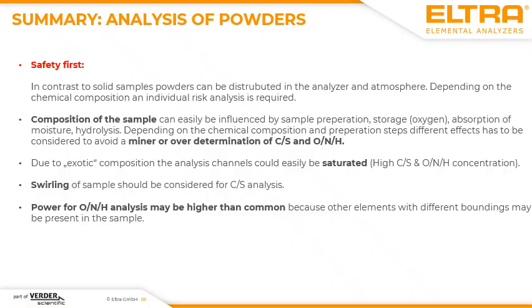Due to the high concentrations in these slags, for example, or powdered samples, it could be that you cannot process your sample in, I would say, a way which is common for you. For example, when you have very high concentrations of oxygen or nitrogen inside the sample, your channels would easily be saturated by typical sample weights of 200, 500 milligrams, for example.